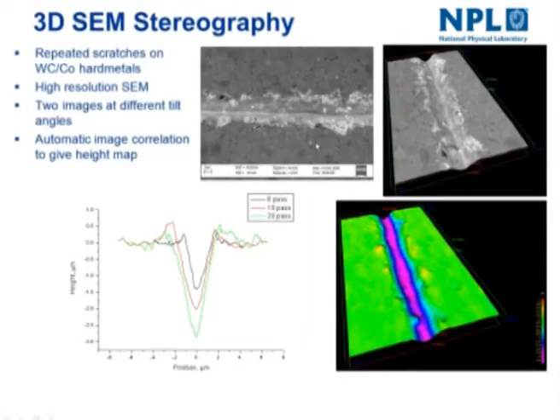Another approach to the similar sort of thing is 3D SEM stereography, and the idea here is that you just use an SEM and you can carry out measurements by taking images at two different tilt angles, and you can then use automatic image correlation to give a height map. This shows the image superimposed on the height map, and this here shows you the color-coded height map directly. You can then do all sorts of analysis on this.